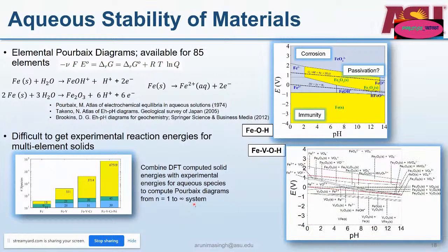In this formalism, they have shown that you can generate these Pourbaix diagrams for, say, systems like iron and vanadium. And you can see that the Pourbaix diagram for iron and vanadium is much more complex than the Pourbaix diagram of the iron, oxygen, and hydrogen system. There are several phases which exist, including several oxides of vanadium and iron, and several ionic species of iron and vanadium.